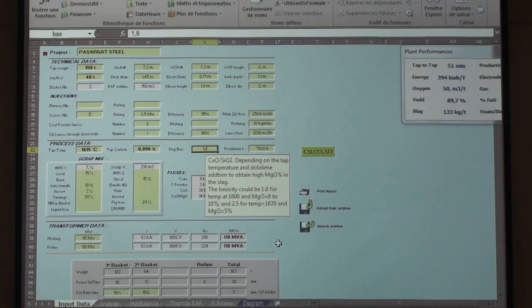So how about this? Normally the construction steels are lower than 1,600 degrees. The molten steel temperature for carbon steel depends. For example, with COS or Consteel, you can tap at a low temperature, even 1580, because you have a lot of bath already, and there is no risk that there is unmolten scrap in the shell. For conventional furnaces, you are not sure about the homogeneity of the bath, so you have to increase the temperature a bit, because the temperature you measure in the door is not necessarily the same everywhere. And then afterward, it depends on the preheating of the ladle itself and the distance between the furnace and the ladle furnace.